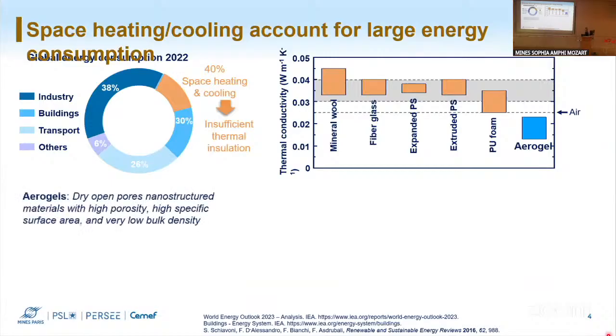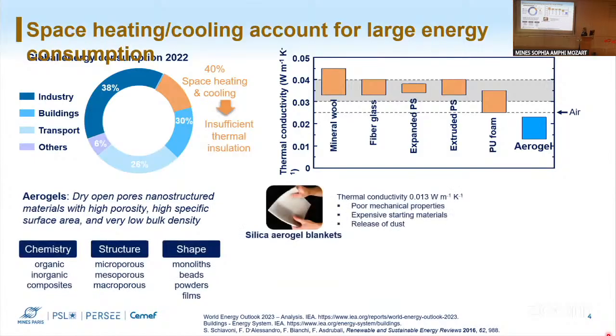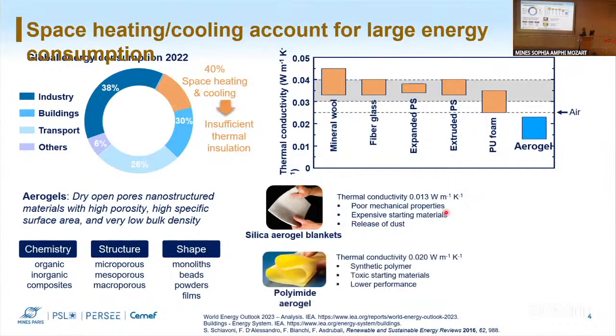What are aerogels? Aerogels are open pore nanostructural materials that have high surface area, very low bulk density, and a very high content of porosity. They can have different chemistry, structure, and shapes. And right now we can find commercially available, not in the neighborhood store, let's say, silica aerogel blankets that have the lowest thermal conductivity. The lowest thermal conductivity that is available for commercial products is 13 milliwatt per meter Kelvin. However, they are very expensive and they have poor mechanical properties. And for this reason, more lately, synthetic polymer aerogels were fabricated to overcome these problems. However, they have a bit lower performance, so higher thermal conductivity.